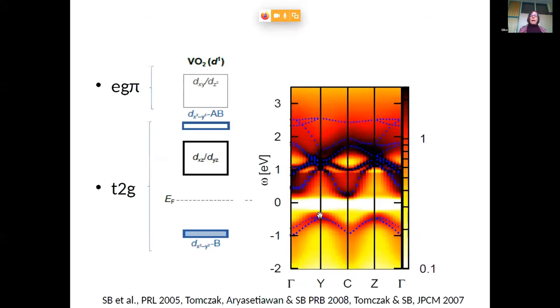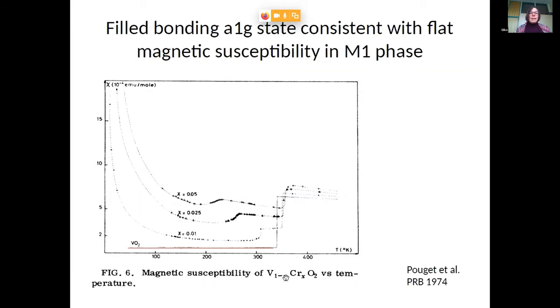Okay, if you say that you have a bonding band split off here, in a D1 configuration, you can easily think of it in the following way. Each of the two vanadiums in the pair gives one electron. They sit together in the bonding state. And that means you necessarily are in a singlet state. That means you have a spin zero here, which is indeed what is seen in experiment. So that is the magnetic susceptibility, again, from Pouget et al., where at low temperatures, that means in the temperature range of the monoclinic phase in the pure compound here, you indeed have a dead flat susceptibility corresponding to the absence of magnetic response because of the singlet formation. So that is consistent with this view.